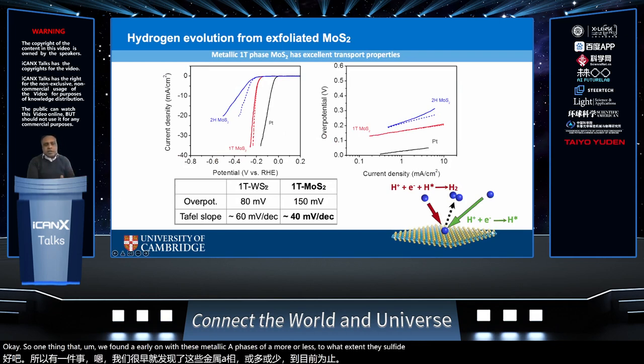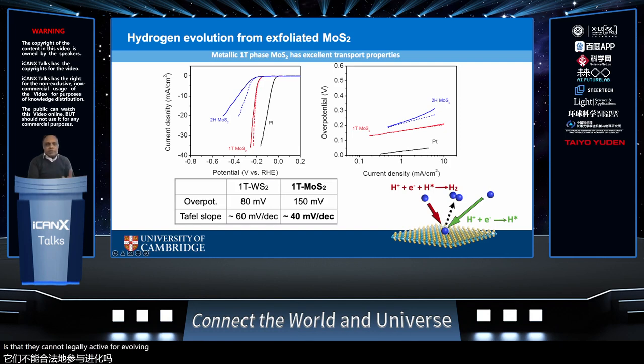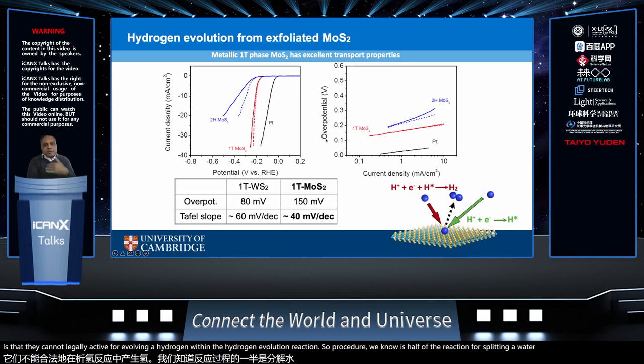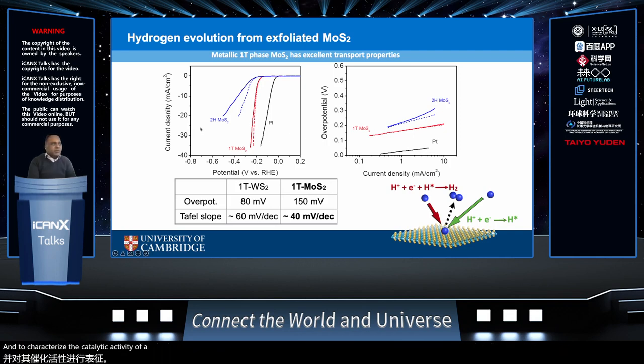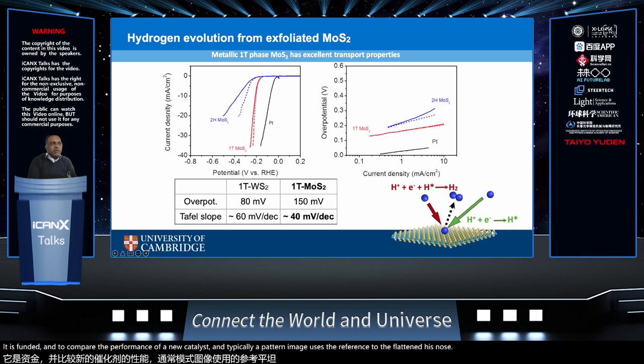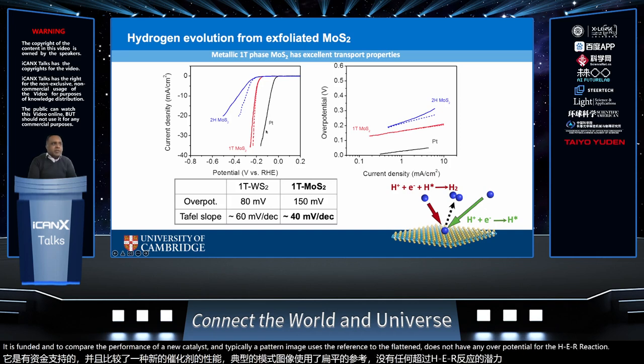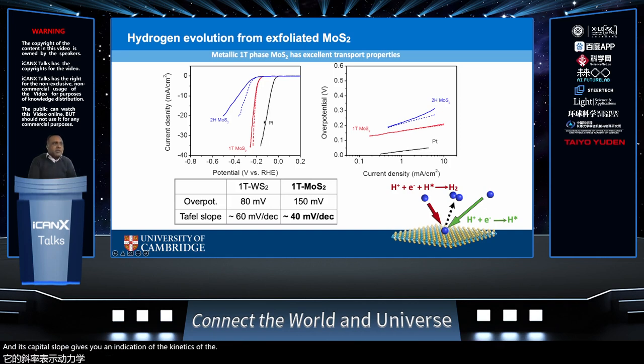Okay. So one thing that we found very early on with these metallic phases of MoS2, as well as tungsten disulfide, is that they're catalytically active for evolving hydrogen within the hydrogen evolution reaction. HER, of course, we know is half of the reaction for splitting water. To characterize the catalytic activity of molybdenum disulfide, one plots what are called polarization curves, where the current density as a function of potential with respect to a reference hydrogen electrode is plotted. To compare the performance of a new catalyst, typically platinum is used as a reference because platinum does not have any overpotential for the HER reaction. And its Tafel slope, which gives you an indication of the kinetics of the reaction, is also quite low.